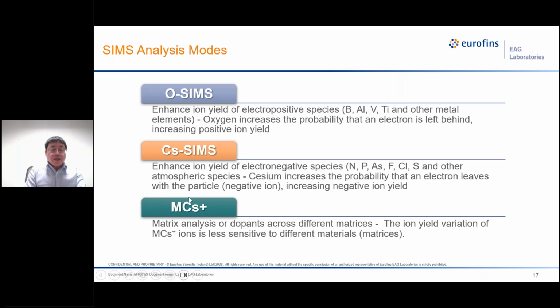Or we can use the MCs+ mode to analyze the matrix or dopants across different matrices. In this mode, the ion yield variation is less sensitive to different matrices. So this mode we use to analyze silicon carbide compositions and any species at the interface.